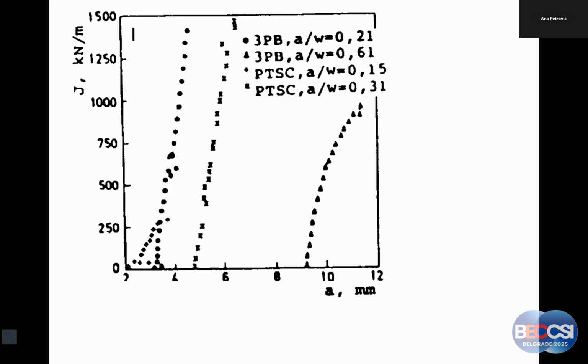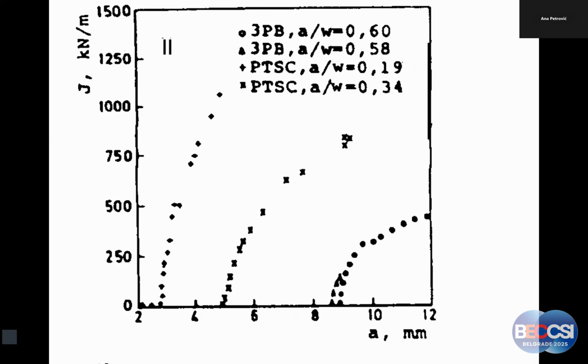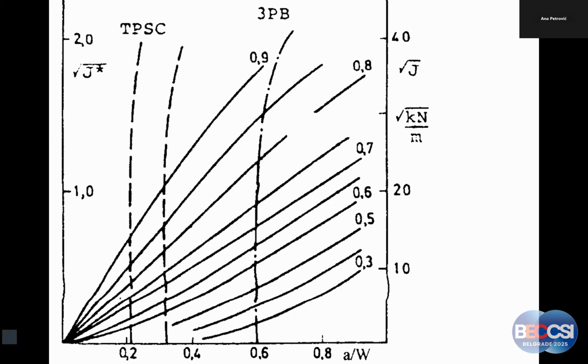This is obvious, the reason is obvious. 3-point bending is a harsher loading than tension. But on the other hand, of course, we like to have a conservative approach. This is why we use 3-point bending. But on the other hand, for example, for pressure vessels, we also like to know the real behavior of the material or structure. That is the question. We'll come to that. So just another figure of these J-R curves. And now they are positioned in a plot with the crack driving force.